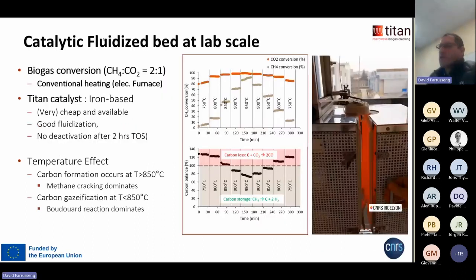So here are, I would say, very first results. First, we have screened catalysts in conventional heating reactors by electric heating, using a model biogas mixture of a 2-to-1 ratio, and we use an iron-based catalyst, very cheap, with good fluidization, because we want indeed to look only at fluidized beds. And what you can see on the top is the conversion of CO2 and methane, which depends very much on the temperature. Basically, we can go to almost thermodynamic equilibrium only at about 900 or 950 degrees C.